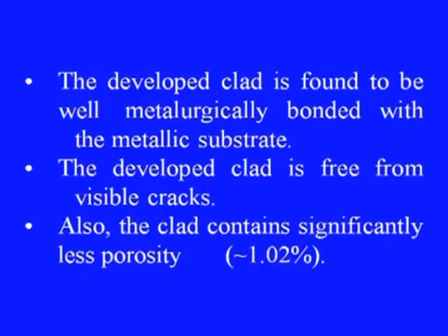The developed clad is found to be well metallurgically bonded with the metallic substrate. The clad is free from any visible cracks, and also the clad contains significantly less porosity, which is almost 1% and which is substantially less. So, this is an image of the clad being developed.